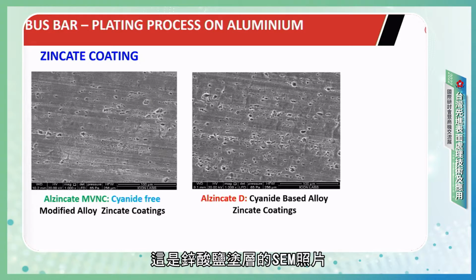Okay, so these are the SEM photographs of zincate coating. So whatever you are observing on the screen is aluminum surface followed by only zincate coating. You can see there are a lot of pores on the right hand side deposit, whereas on the left side the deposit pores are much lower. So the left side coating contains Alzincate MVNC, which is the non-cyanide based alloy zincate.